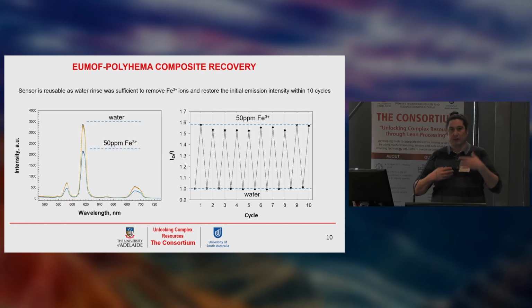And we want, obviously, this process to be reversible, so we can easily reuse the sensor or reuse the composite. And this cycles between putting the MOF composite into water and then into a ferric iron solution, and repeating that process and going back and forth. And you can see that the response is very reproducible. So we can do this over multiple cycles without any significant loss or change in the response of the composite.